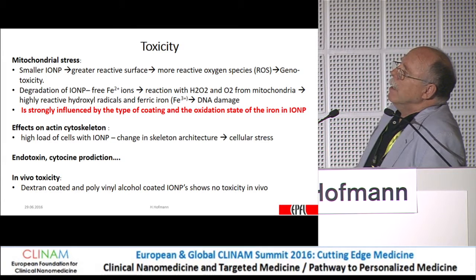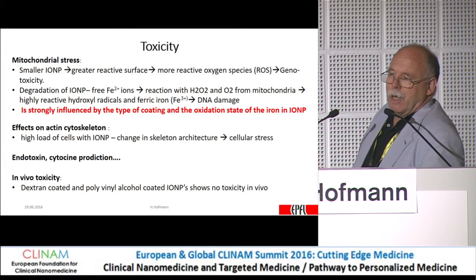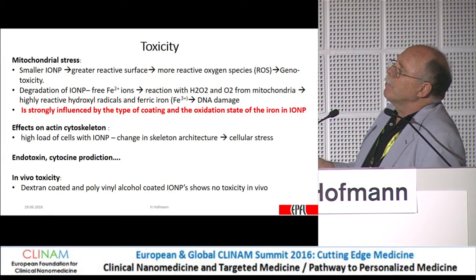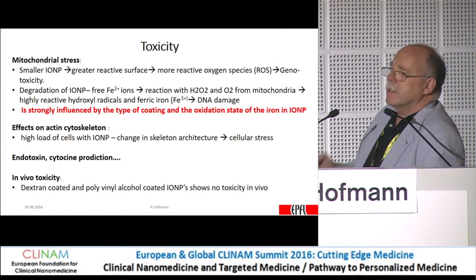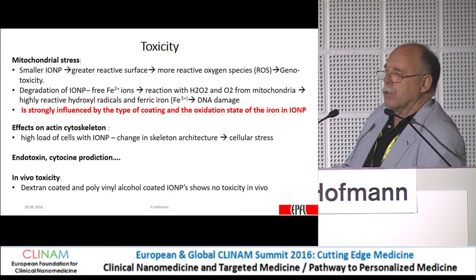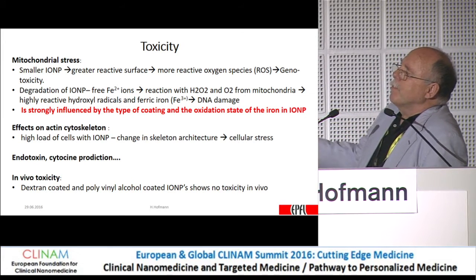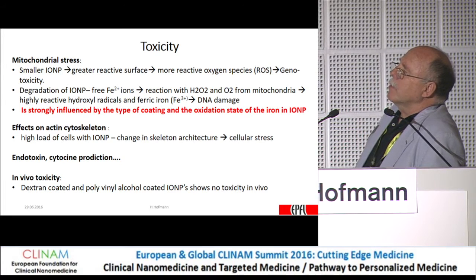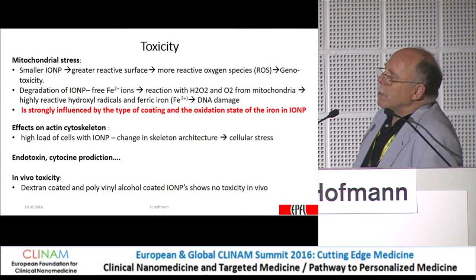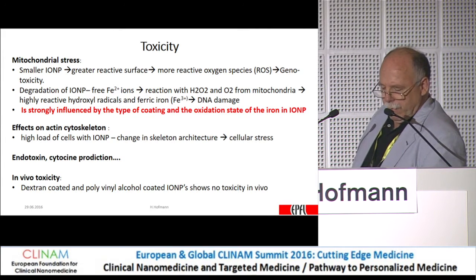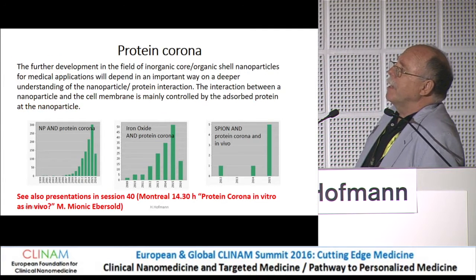But anyway, all this tox stuff is strongly influenced by the type of coating and the oxidation state of the iron oxide nanoparticle. Yesterday in the afternoon there was a very good session about toxicity of nanoparticles, and it was also stated that dextran-coated iron oxide nanoparticles are not toxic, at least not for that aspect they investigated, cytokines and others. Then we have effects on the actin skeleton and so on. But in vivo, there is no toxicity with dextran-coated nanoparticles, so we are relatively safe.